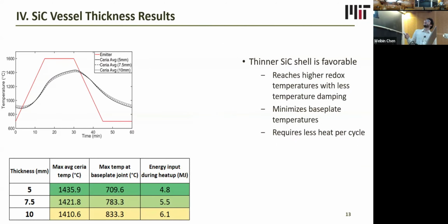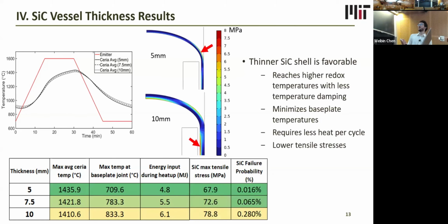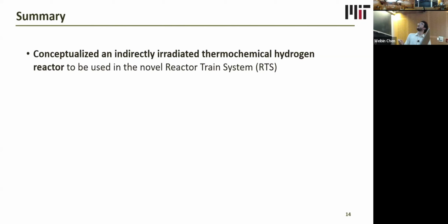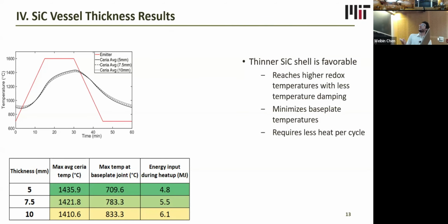What we can see in this plot is the ceria average temperature in solid black for the 5 millimeter, dashes for the 7.5, and dots for the 10 millimeter. Predictably, when we go to thicker silicon carbide, we have a greater temperature dampening response. But what our models allow us to do is really quantify that, and we can see the exact difference in the maximum average ceria temperature that is attained. While this might not seem like a lot, this is actually going to end up being a lot in terms of reduction extent at these temperatures.